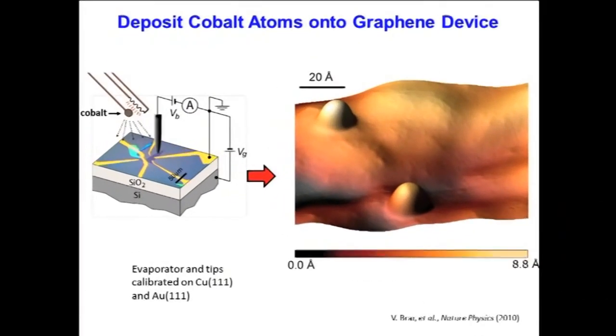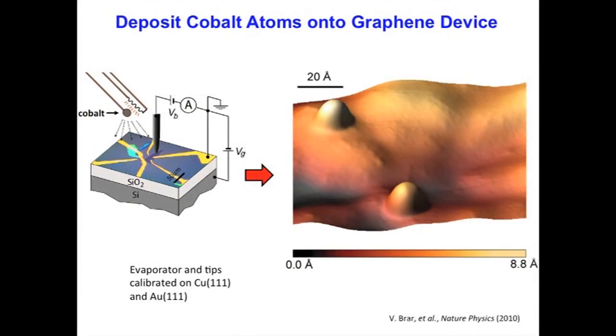Motivated by this, we dropped atoms down onto graphene. We dropped different atoms, and one of the first we looked at is cobalt. We evaporated cobalt atoms onto a gated graphene device at low temperature so that the atoms would stick and not move around, and then we took STM images. Here you see an STM image of a gated graphene device on silicon oxide, where you can see two cobalt atoms. There they are.